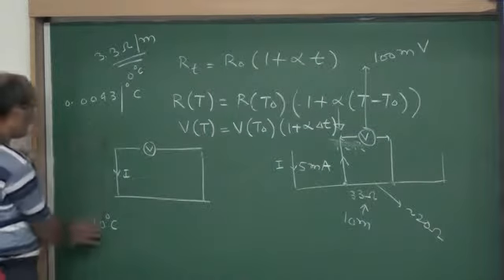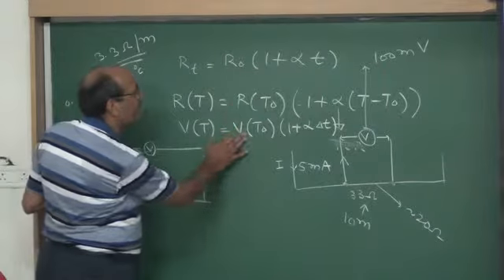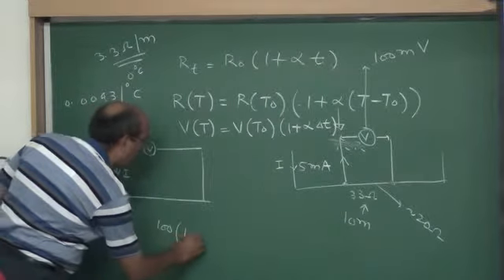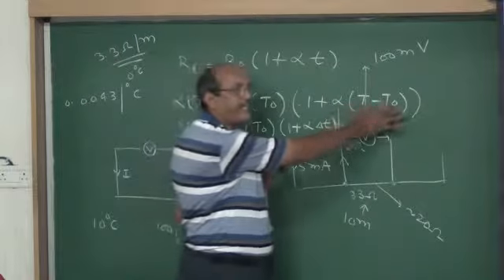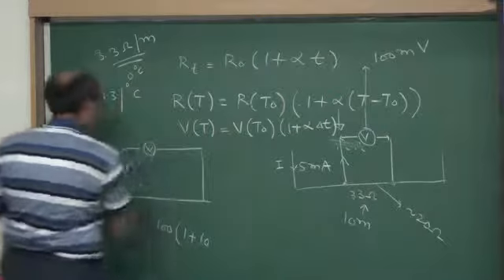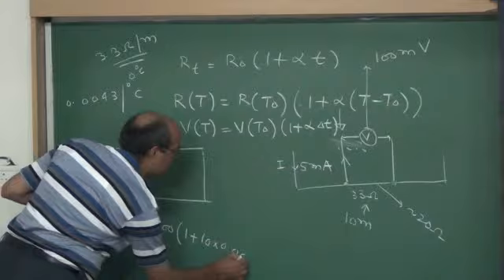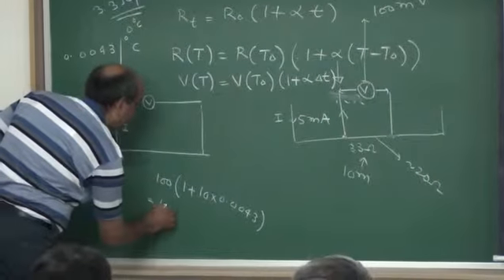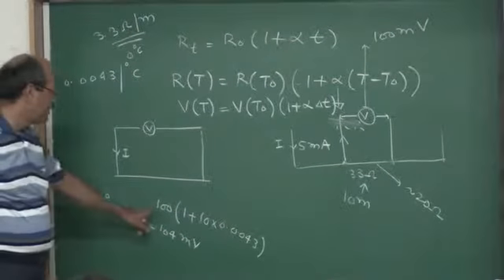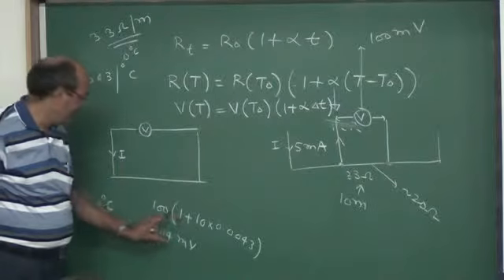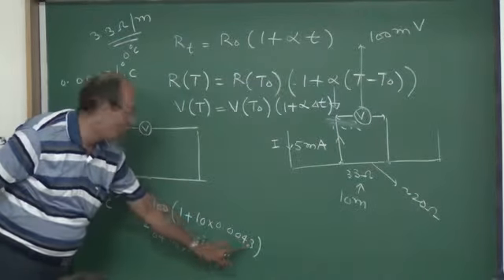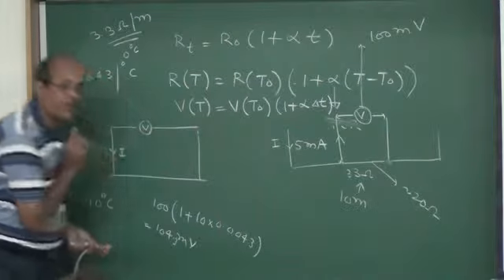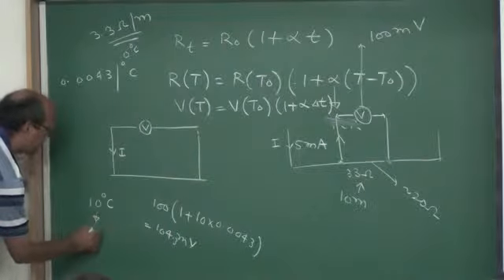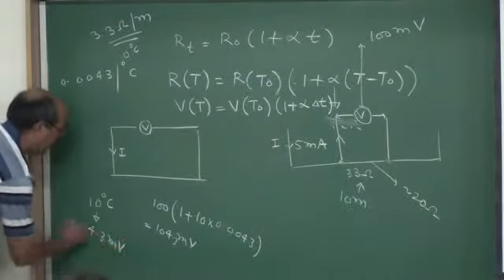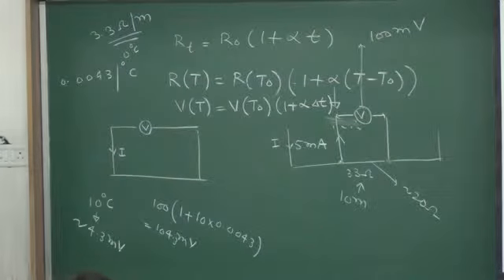So here, if you raise the temperature by 10 degree centigrade, by applying the same formula, right now it's 100 millivolt. So 100 millivolt into 1 plus, we are raising the temperature by 10 degree Kelvin or 10 degree centigrade. So this is 10. The value of alpha is 0.0043. If you calculate this, it comes out to be around 104 millivolt. So the decimal comes here, and this becomes 104.3. Therefore, if you increase the temperature by 10 degree centigrade, the voltage will increase around 4.3 millivolts, and we can easily measure this voltage by a normal multimeter.